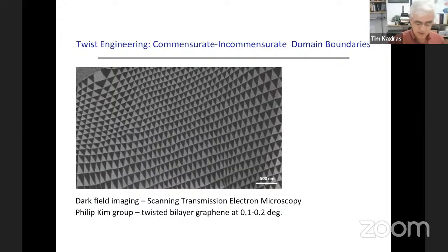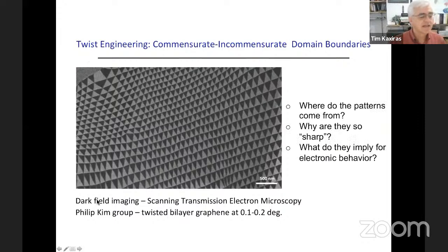And these are the kinds of pictures that you see from experiment. So this is a dark field imaging scanning transmission electron microscopy picture from the Philip Kim group. And it's a twisted bilayer graphene at about 0.1 to 0.2 degrees twist. And you see these really very regular and very large scale beautiful patterns of different regions. So where do the patterns come from? Why are they so sharp? What do they imply for electronic behavior? A lot of progress has been made in answering these questions, and we'll be addressing some of these from the single particle picture.